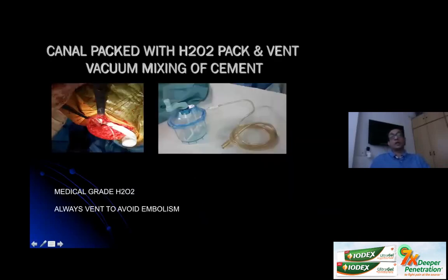After that, once you've put your cement restrictor, give a nice thorough wash with your pulse lavage, so as to remove all the dead debris, the bone particles, the blood, etc. Then vent your canal and pack it with sterile hydrogen peroxide, so that you maintain this dry bed of bone which you have prepared. Always use a vent, because if you do not use a vent, then you can end up having some amount of embolism from either the trapped air or the oxygen that comes out from your hydrogen peroxide.